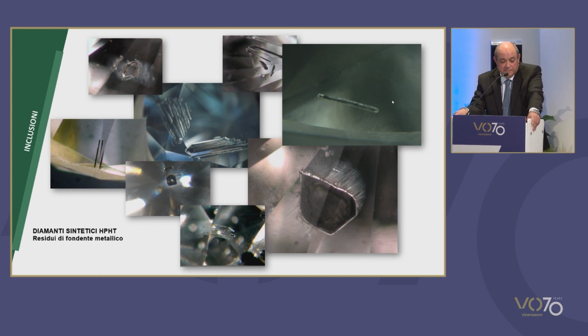If we look at high pressure, high temperature synthetic diamonds, well, the tendency is to have highly pure diamonds, but sometimes there can be remnants of metals, because with this method we use a metal alloy in order to synthesize the crystal diamond. So you can observe such a situation with a given orientation, and if you observe them, they actually look like metal pieces.